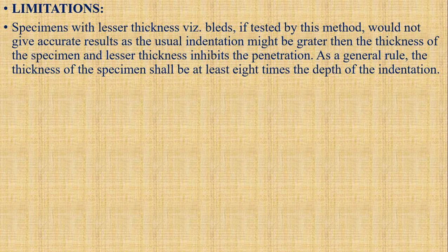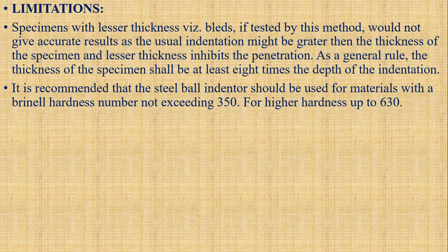Limitation: specimens with lesser thickness, for example blades, if tested by this method would not give accurate results, as the usual indentation might be greater than the thickness of the specimen, and lesser thickness inhibits the penetration. As a general rule, the thickness of the specimen shall be at least 8 times the depth of the indentation. It is recommended that the steel ball indenter should be used for materials with Brinell hardness number not exceeding 350, and a carbide ball for higher hardness up to 630.